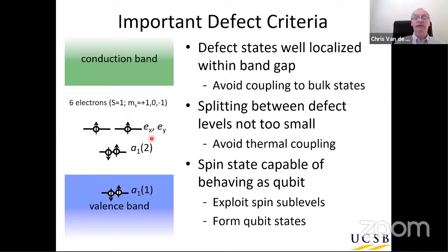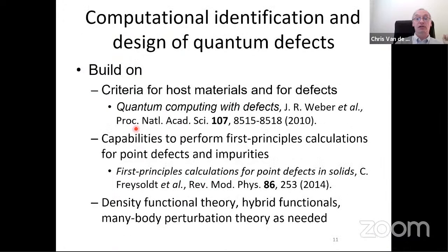So this second E state within the band gap gets occupied, and you get a spin state. And it turns out that for applications, this is the most desirable configuration. So what I'm showing here is that, of course, there is a direct coupling between the occupation of the states in your defect center and the charge state of this defect. And that's something we're going to be talking about as an important criterion for designing such defects.